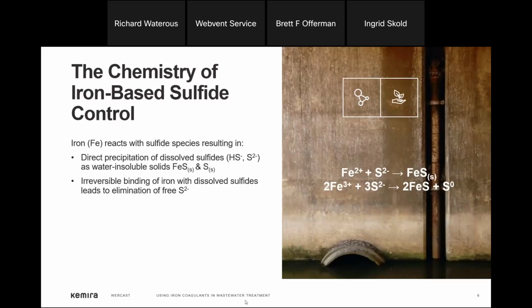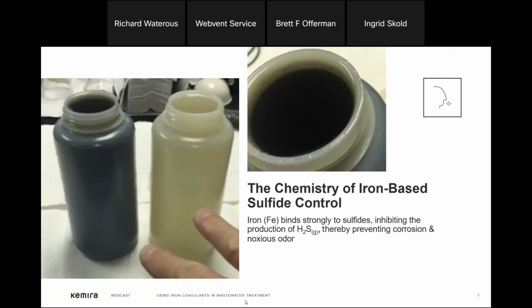Many of our customers add iron many miles upstream of the treatment plant to maintain low levels of dissolved sulfides throughout the collection system. This is unlike other chemistries which provide a more localized solution. Ferric and ferrous chloride and ferric and ferrous sulfate can be utilized for effective H2S control. The robust iron sulfide complex formed with iron addition keeps sulfides bound throughout the entire treatment process, including anaerobic digesters, preventing the release of harmful H2S gas downstream, unlike competing chemistries.